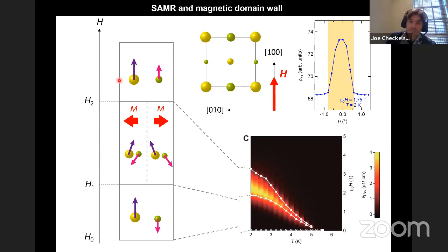So in this system, you have at low temperature this ferrimagnetic ordering. And if you imagine in zero field, or very low field anyway, with field along say the 100 axis, this is what the magnetic order looks like. So if you apply a huge magnetic field along 100, eventually you're going to flip the moments. I mean, eventually the moments will give up and flip. And an interesting thing is that at some intermediate field, the spins will go through a so-called flop transition, where it turns out they can lower their energy a little bit by flopping, so that they now agree a little bit with the Zeeman field, but retain some of the exchange, the sort of ferrimagnetic exchange.